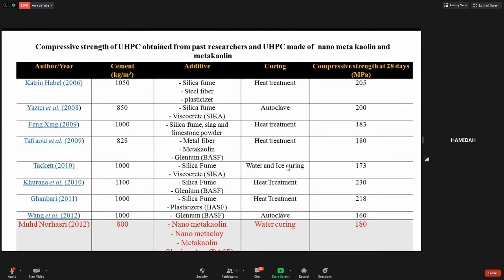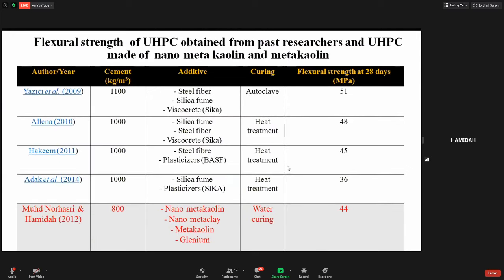Similarly, the flexural strength obtained is equal or higher despite the lower cement content used. It is confirmed that the inclusion of 1% nanometakaolin and 1% nanometaclay enhanced the compressive and flexural strength, and both strengths were achievable from UHPC specimens cured in water.